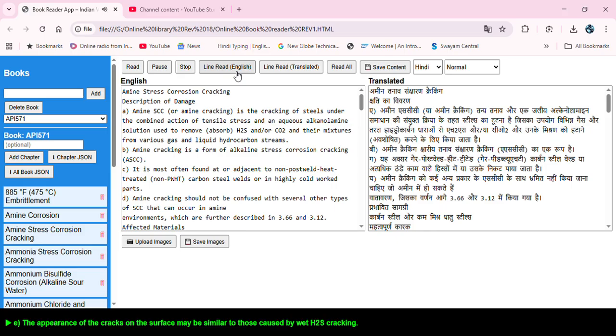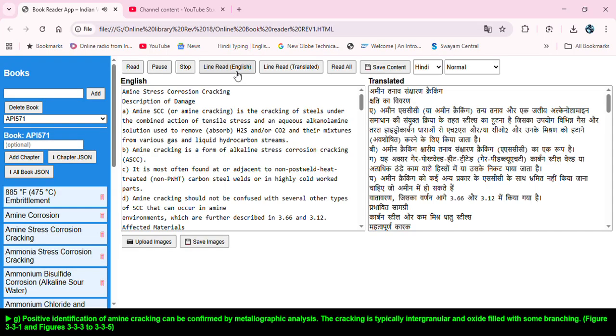E. The appearance of the cracks on the surface may be similar to those caused by wet H2S cracking. F. Because residual stress is a driving force for cracking, cracks can occur on the process side opposite external attachment welds. G. Positive identification of amine cracking can be confirmed by metallographic analysis. The cracking is typically intergranular and oxide-filled with some branching. Figure 3-3-1 and Figures 3-3-3 to 3-3-5.